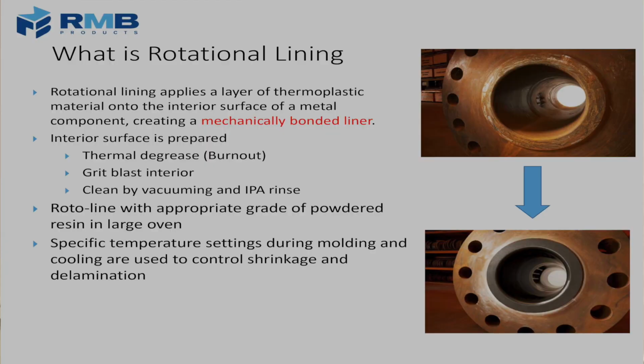What we do differently here is that we want that resin to stick. So there are certain steps that are going to be taken so that when that resin is poured into the cavity, it bonds to the prepared metal. So we count on that mechanical bonding to provide that corrosion resistance inside the metal part. We start with the thermal degrease or burnout, and then we grit blast the interior with the appropriate blasting media, and then we clean it by vacuuming it and putting an IPA rinse. I'm going to go into more detail about how the rotational lining process works, but basically the difference is we want that resin to stick. It's very important that it adheres as a bonded liner.